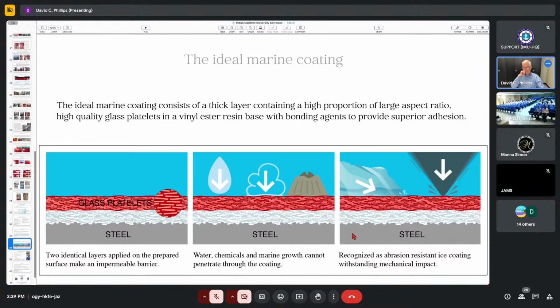This coating will not affect it. It will not contaminate. Interestingly enough, this coating is classified ice abrasion resistant by classification societies, Polar Class 1 to Polar Class 7. What does that mean? It means you can sail a ship protected with this coating in any sea, in any season, and it will have classification okay from a coating point of view. It also means that you can reduce the thickness of the steel on an ice-going ship by up to 3.5 millimeters if you use this coating.